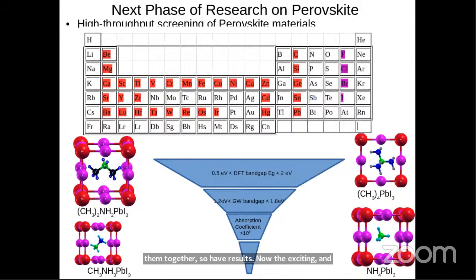And then we tend to look for material for solar cell absorber. The first thing we look at is the DFT band gap between 0.5 electron volts to 2 electron volts. Also, we do GW band gap to select material that best fits for solar cell absorption. We are also looking at materials with absorption coefficients that are greater than 10 raised to power 5, and a whole lot of properties that will be useful for our solar cell material.